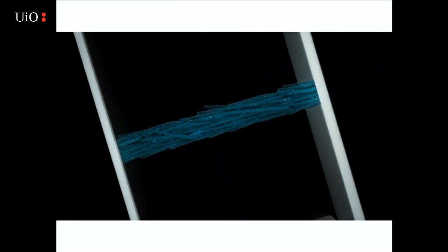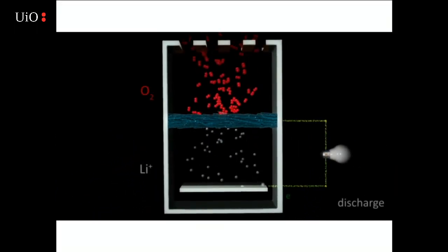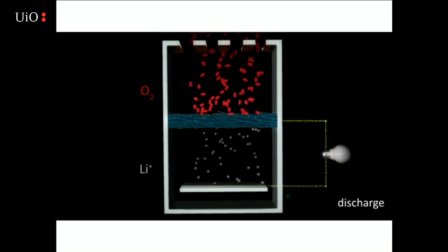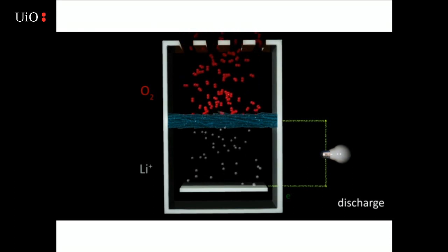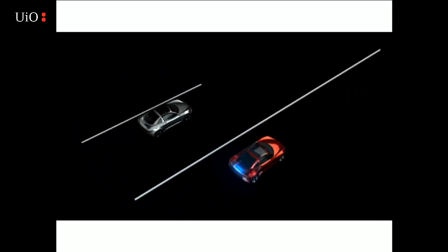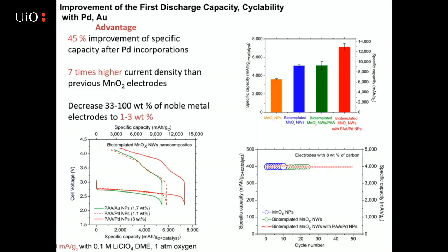And then we can test it as a lithium-oxygen battery electrode. And that's my car. No, this is a car my kids wish that we had, but I actually have a Chevy Volt, which I love. But the idea is that you'd be able to go twice as far. And so what we actually saw from these experiments, we had 45% improvement in the specific capacity, and we had 7 times higher current density than previous manganese oxide electrodes. And it worked best when we had the combination of the biotemplating and the addition of the high surface area and the addition of the palladium nanoparticles.